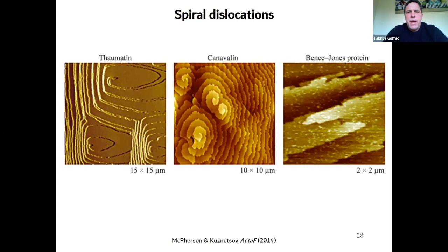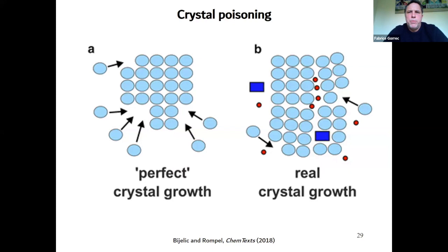You may have a problem during the growth because basically what's happening is at the surface of the microcrystals, you will have different two-dimensional patches that grow independently. And obviously at some point they may clash with each other, which is called spiral dislocation. So that creates a lot of defects in the crystals. Another problem during growth is what's called poisoning. So during the crystal growth, you may have partially denatured proteins or other contaminants that are integrated in the crystal lattice. And it's actually the main cause of termination of growth.